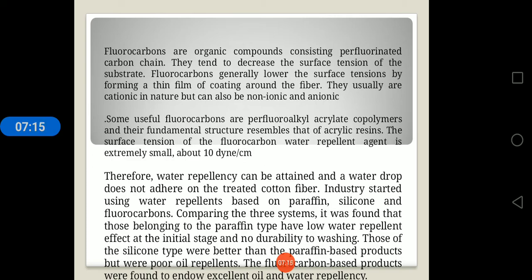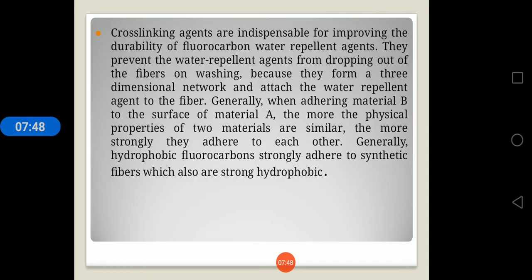Industry started using water repellents based on paraffin, silicon, and fluorocarbons. Comparing the three systems, it was found that those belonging to the paraffin type have a low water repellent effect at the initial stage and no durability to washing. Those of silicon type were better than the paraffin based products but were poor oil repellents. The fluorocarbon based products were found to have excellent oil and water repellency.